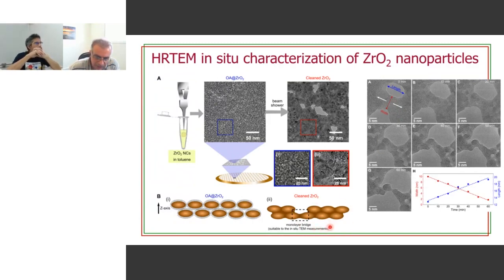I mean, they will grow into larger structures. This is what is basically more favorable from the thermodynamic point of view, to sinter those nanoparticles, but locally, in some specific positions, you will see that some regions actually shrink, and eventually they form a pair of nanoparticles that are just joined together by a very thin neck. And this happens because of the surrounding strain fields that eventually lead, in this particular position, to, let's say, a tensile strain that eventually leads to what we call the desintering, or breaking, of the two nanoparticles. Okay. So that's the key idea. The tensile stress promotes local desintering instead of sintering.